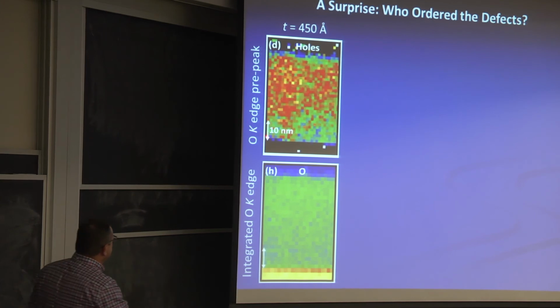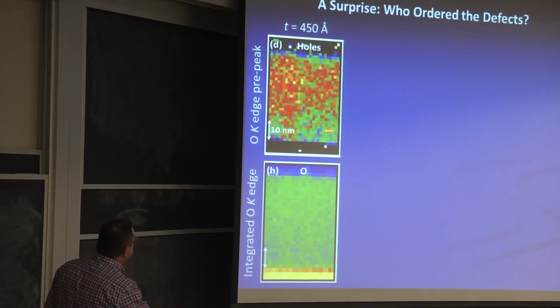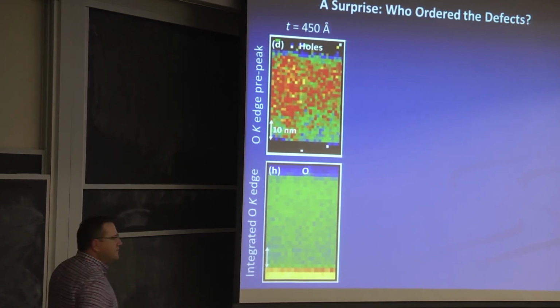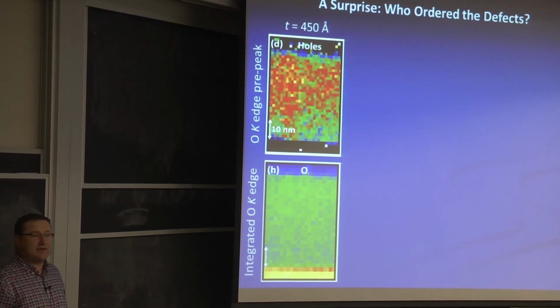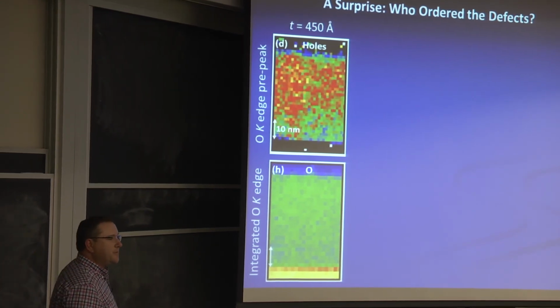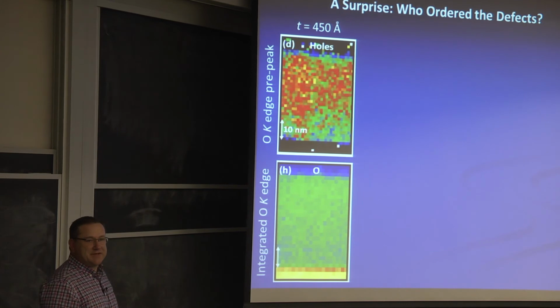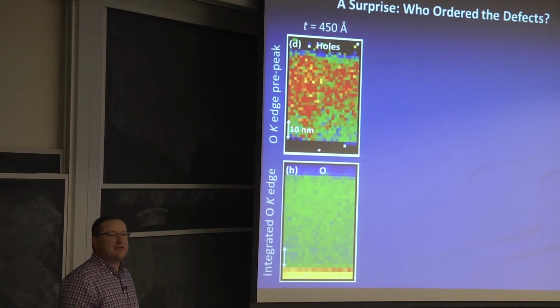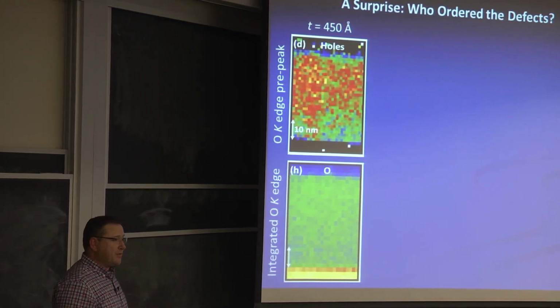You look at the structural map, it's perfect, and then the electron microscopist shows you this, and you're like, oh my gosh. I mean, it just looks awful. It's heterogeneous, it's lumpy, and in particular, this part got us really interested and excited. There's a clear depletion of the charge carriers at the bottom of the film. That's obviously why this thing has a dead layer of about 10 nanometers thick. It doesn't have any holes left at the bottom of it.